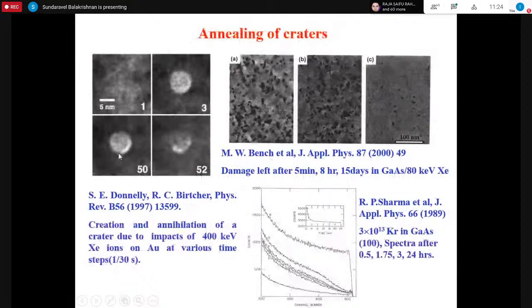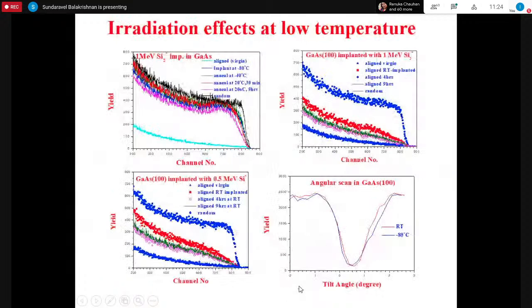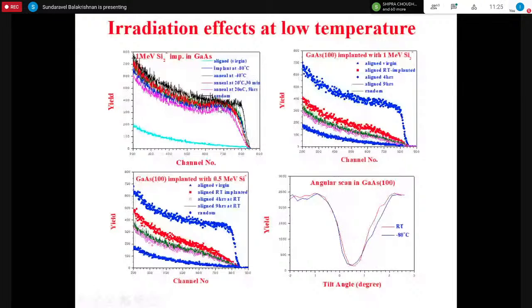Okay, here with TEM, people have shown that upon irradiation craters will be there. If you leave it for some time, those craters will anneal out and it will be decreasing. Same thing can be seen with RBS. Initially, damage will be more, and after some time, that yield will be reduced. We have done some low temperature experiments in gallium arsenide also. At low temperature, if you do the irradiation, there won't be self-annealing and damage will be more. But if you do the same thing at room temperature, due to self-annealing, the defects produced are less.